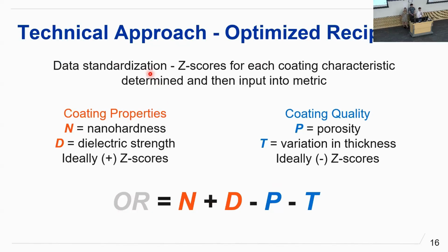So our optimized recipe. As Connor mentioned in the background, we want a high nano hardness and a high dielectric strength. These are properties that need to be high for this coating to be used in the industry. And we want a low porosity and a low variation in thickness. So coating properties on the left, N and D, represented in the optimized recipe equation, and then coating quality, P and T, are both negative because we want them to be low values.